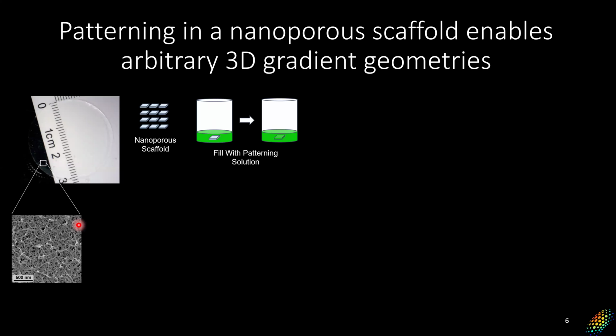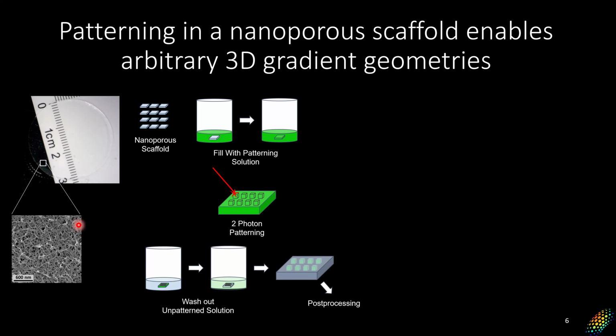You can then take this sponge-like structure and fill it with a liquid patterning solution, such as a polymer resin. It can be other things as well. And then we do two-photon lithography to attach this patterning material, or use it to fill in the pores of this scaffold. And then we can wash out anything that hasn't been patterned. So you're just left with these three-dimensional structures embedded inside of this porous scaffold material.